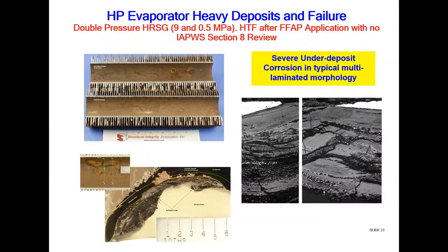So this is an example from a combined cycle plant, an HP evaporator using an FFAP. This is a film-forming amine product with something else added to the active ingredient. And you can see the heavy internal deposits here on the inside surfaces of the tubes. And when we cut those open, you see these very heavy deposits here. And when we look at these in detail, we find that these are multi-laminated, which is the typical structure that we see for under-deposit corrosion. So this is a good example of under-deposit corrosion.